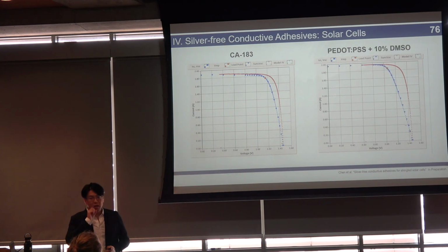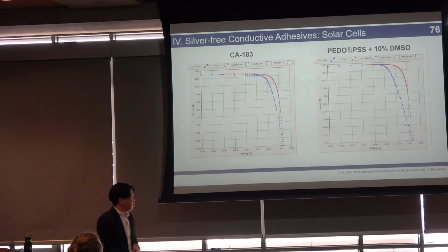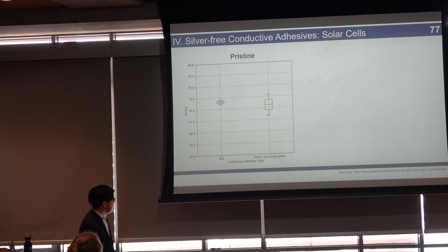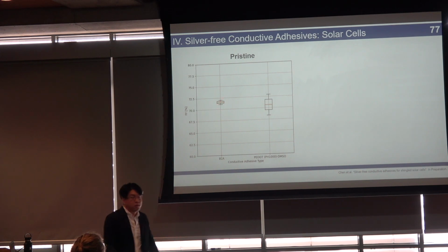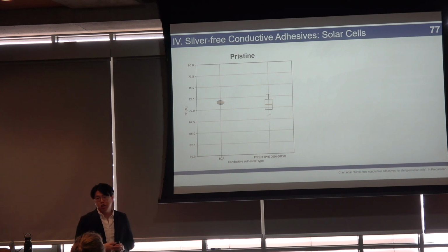But the moment you add DMSO as a small molecule dopant, your fill factor is largely recovered. We can compare the fill factor between the two, and we see that actually they're very, very close. For the commercial standard, that's silver and epoxy, you have a fill factor of about 72%, something like that, whereas with PEDOT:PSS, you can actually achieve about 71%.